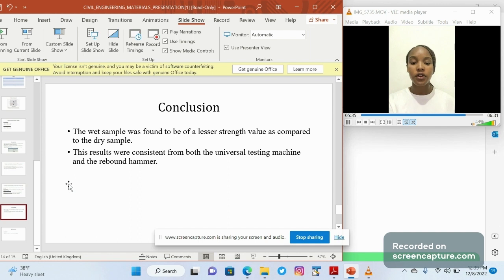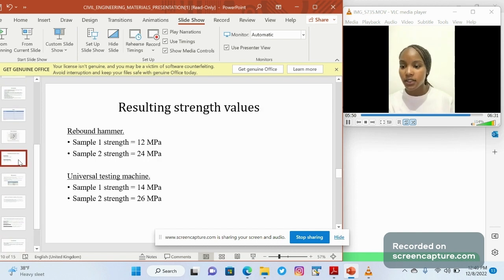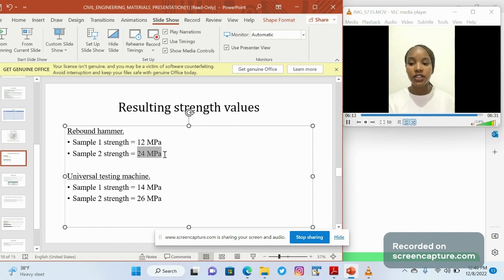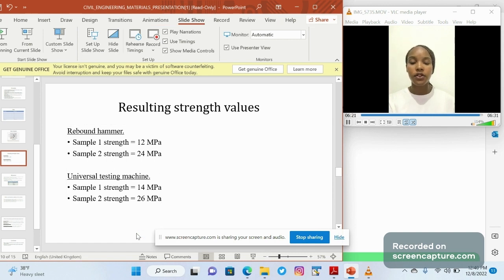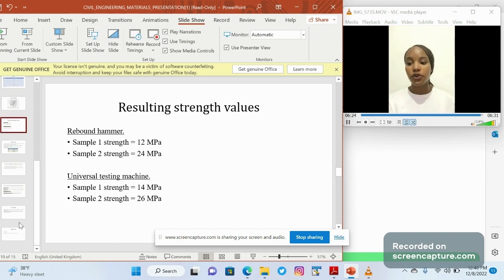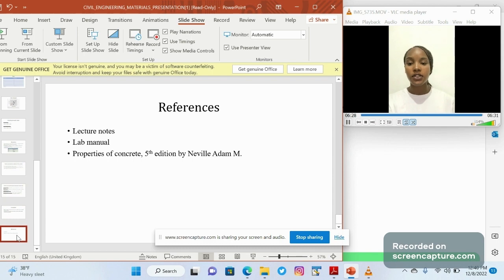Our conclusion is the wet concrete cube had lesser strength value compared to the dry concrete cube, and the results from both the rebound hammer test and the universal testing machine were found to be consistent, because as we look at our data, we got 12 megapascal on the rebound hammer and 14 megapascal on the universal testing machine for the wet concrete cube, and we got 24 megapascal on the rebound hammer and 26 megapascal on the universal testing machine for the dry concrete cube. Therefore, there was not much difference when it came to the comparison between the rebound hammer and the universal testing machine. Thank you.